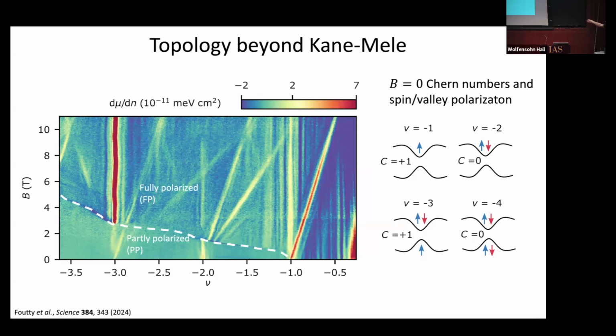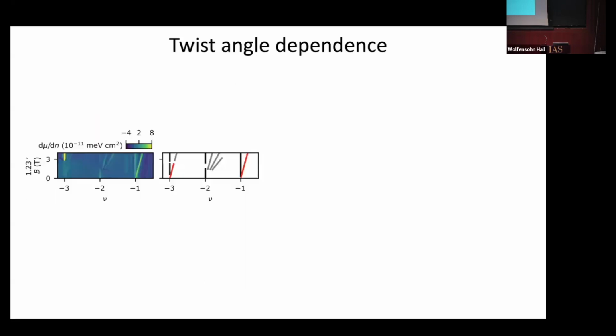We think actually that we're in this scenario where both of these diagonal lines point off in the same direction. So we think we're in a limit where both of the Moiré bands for a particular valley have the same Chern number. So you have to consider multiple bands, not just 2 bands. It's not just a Kane-Mele model, but actually you have to consider even more bands to get to a net Chern number of 0. And similarly, at 4, it's not shown here, we think we've occupied both pairs of Moiré bands, of the first 2 Moiré bands.